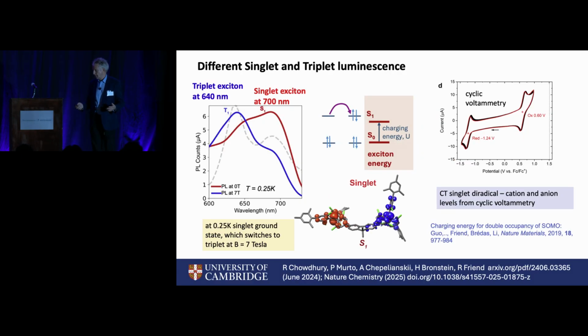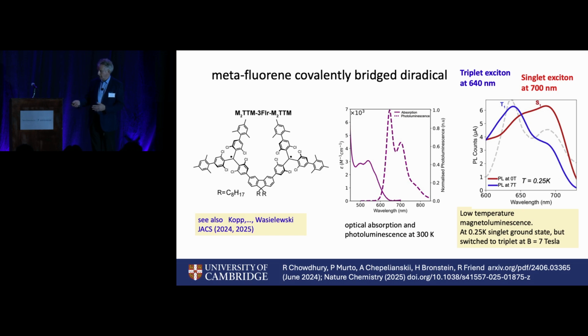I should have said, I forgot to say that the color, the right-hand side, the way we could switch between the triplet and the singlet was to take the device down to a low temperature and apply a magnetic field to switch the spins from antiferromagnetic at 0.25 Kelvin to ferromagnetic by applying 7 Tesla to swing the spins around.